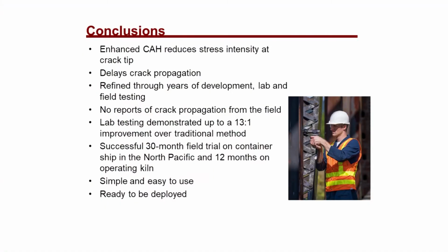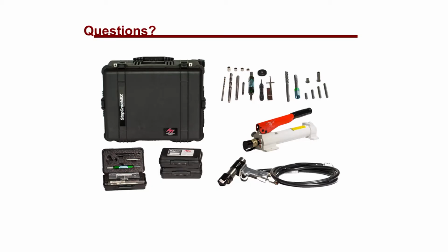In conclusion, using the enhanced crack arrest really reduces the stress intensity at the crack tip. We know that you're never going to repair a crack; you have to take it out and replace the structure. But you can mitigate it, and this is a really good way to mitigate it, by putting it through this process and putting it into residual compressive stress. We've done a lot of work on this: a lot of engineering thought behind it, the FEA work, analysis, a lot of lab testing, a lot of field testing, and again, I've not had any negative feedback. If you've heard of something negative, I'd like to know, but we think it's pretty good stuff. Well, I'll open it to your questions.